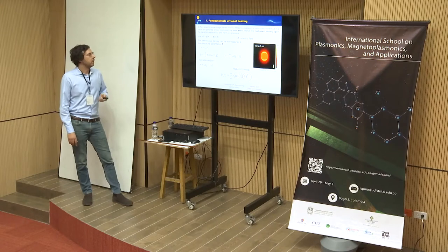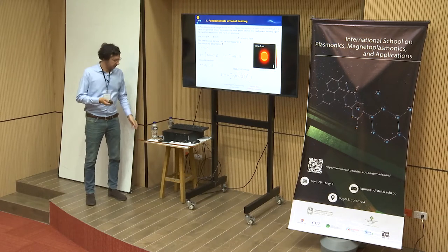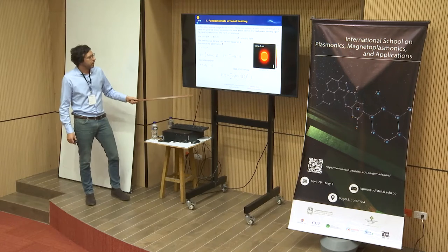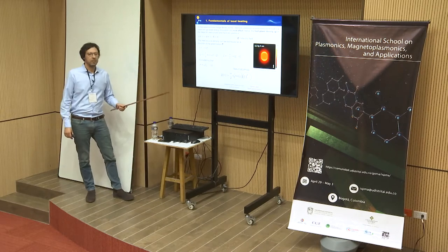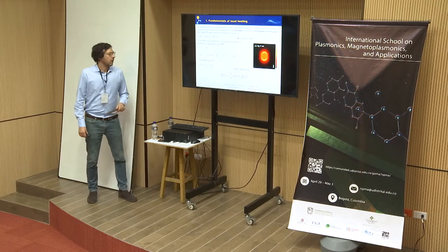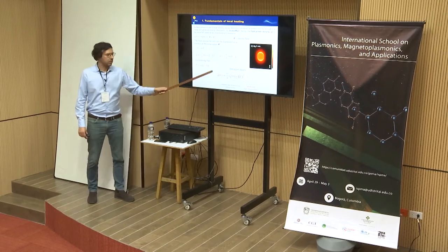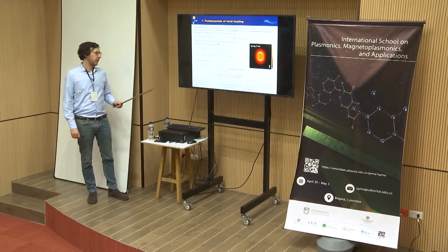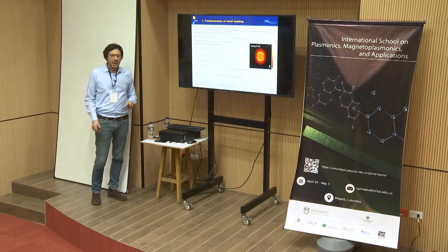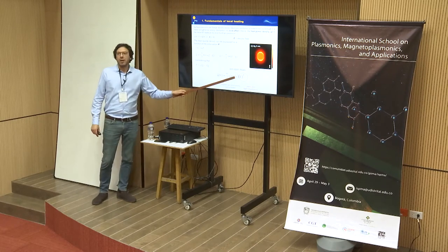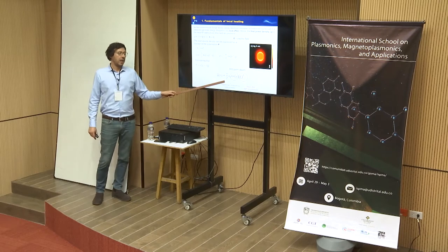So knowing the current coming from the surface plasmon excitation and the electric field which is produced in the plasmons, what we end up with is that the heat source power density depends, of course, on the frequency of excitation, on the imaginary part of the electric permittivity, and also on the square of the electric field. This is an interesting formula, because we can see that to have really high energy and a high gradient of temperature localized at the nanoscale, we would need really strong electric fields confined on the surface of our materials, but also very high optical losses.